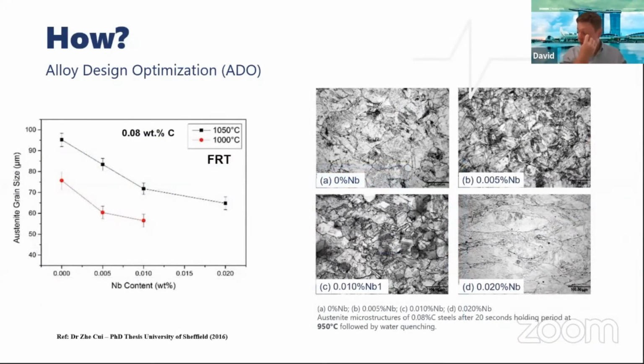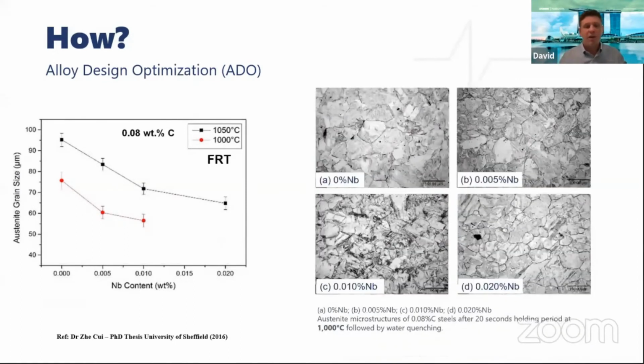Showing some microstructures on the figures shown by Dr. Patel, as you can see, the austenite grain size prior to transformation is strongly affected by niobium, even by a 50 ppm addition of niobium in a 0.08 carbon steel with finishing temperatures above 1000 degrees C without any TMCP, right? It's a very high finish rolling temperature. You can still see a positive influence on the refinement of the austenite grain size. As the niobium grows higher, you can even see the recrystallization stop. But with higher finish rolling temperatures, what we see is actually a grain refinement.